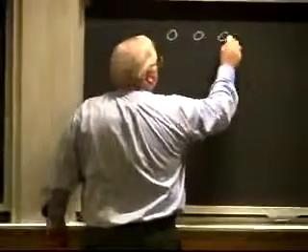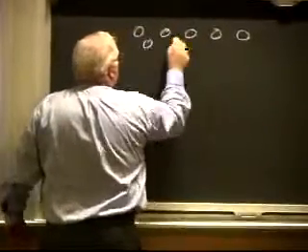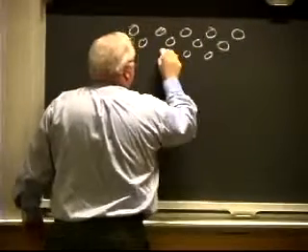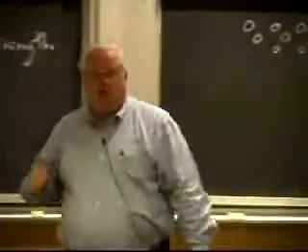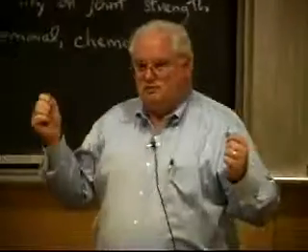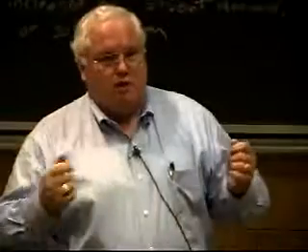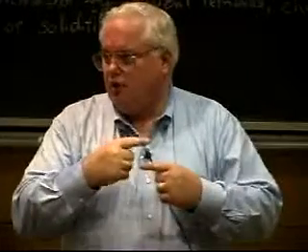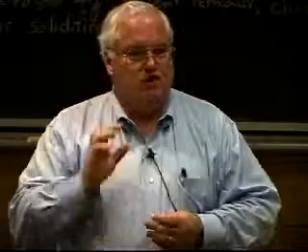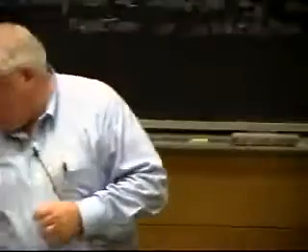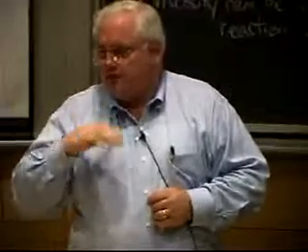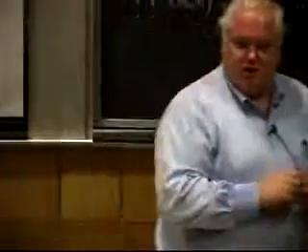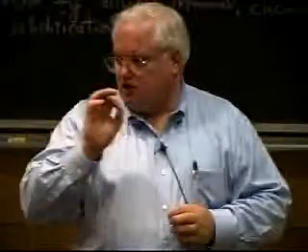So it turns out Post-it notes actually have an array of little adhesive dots, which are basically just as strong as the Scotch tape. But what you're doing with Post-it notes is basically a perforated adhesive. And so it's easy to peel apart because you've basically got fracture mechanics working for you. You've got these cracks, if you will, or non-adhered regions in between. And if you're careful and you get the right type of dirt, if you blow a little bit of fine dirt on the Post-it note adhesive, you actually can start to see the pattern.